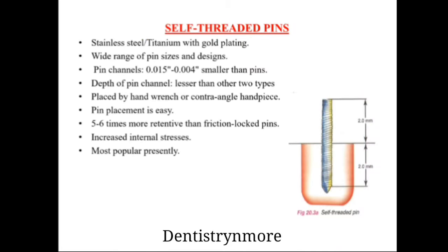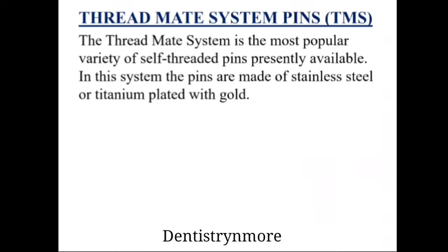Next one is the self-threaded pin. It is stainless steel or titanium with gold plating, and there is a wide range of pin sizes and designs. The pin placement is easy. It gives 5 to 6 times more retention than the friction locked pin. There are increased internal stresses, and it is the most popularly used pin. Here you can see the figure of the self-threaded pin.